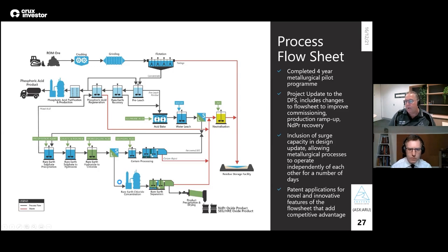We then take that rare earth chloride, evaporate off some of the water, and then put it through a small SX circuit for removing the SEG: samarium, europium, gadolinium, and heavy rare earths. And then following that, it goes through to another solvent extraction circuit that then removes the NdPr, which we can then precipitate out with oxalic acid and calcine off to a rare earth oxide. And this has been tested ad infinitum. You've done this for years. We've done about 4 years of piloting on this flow sheet.